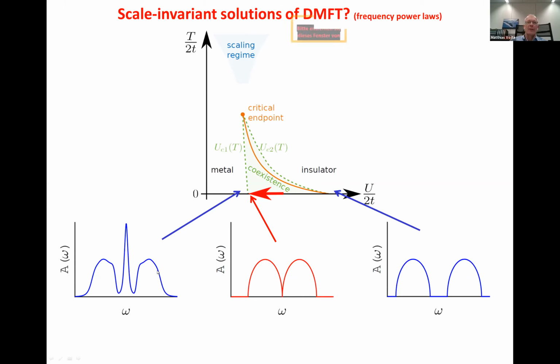Independent of this, there is a metallic phase, which starts out with this blue spectral function on the left. And then as you move towards the right on the phase diagram, this quasi-particle peak in the middle gets less and less weight. In other words, it becomes narrower and narrower. This is essentially saying that the metallicity becomes weaker and weaker, until you go to this point here.